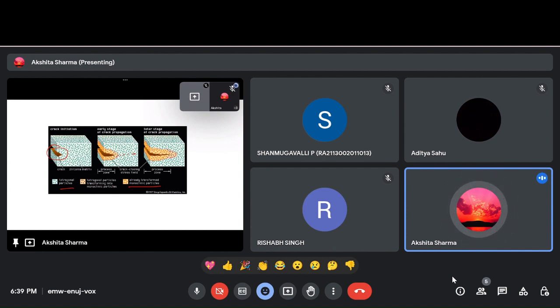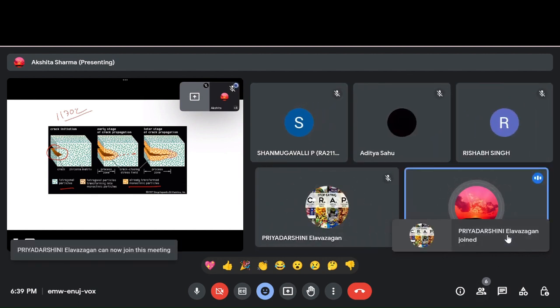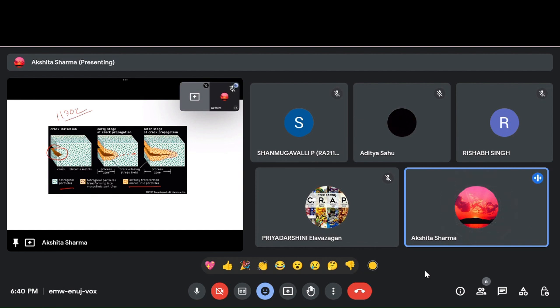I understand that this crack would have been possible because there was a temperature drop, because tetragonal is stable at 1170 degrees Celsius. So the crack developed because there must be some temperature drop. Obviously, monoclinic phase is stable at room temperature. But why did it go into the monoclinic structure? What is happening at the fundamental level?